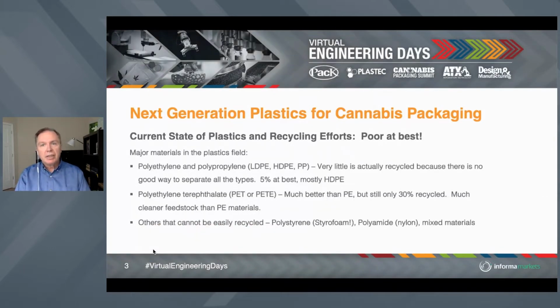So let's talk about recycling of those conventional materials first, because that is still a possibility for all of this. The major materials in the plastics field, the polyethylene and the polypropylene, all of this that we're going to talk about is fossil fuel based. So the polyethylene and the polypropylene, that is low density, linear low density, high density, regular polypropylene. Very little of this is actually recycled because there's no good way to separate the types of these polyolefins, as we refer to these. At best, about 5% is recycled, and most of that is high density polyethylene. Think milk jugs and things along those lines, but realistically, most high density polyethylene does not get recycled.